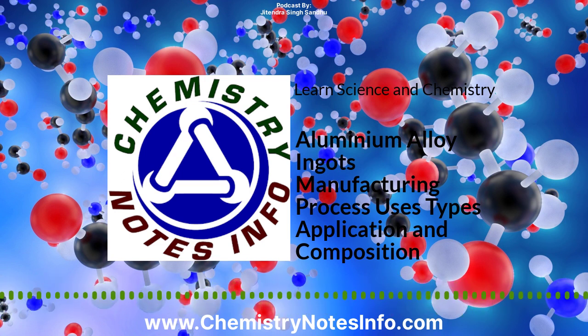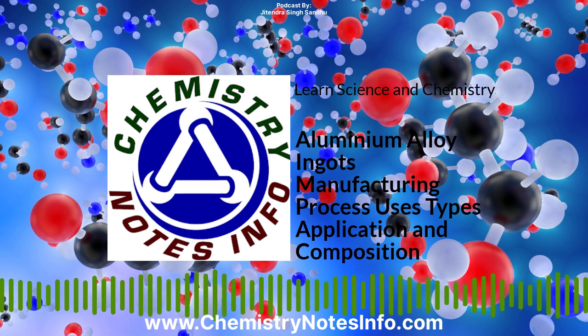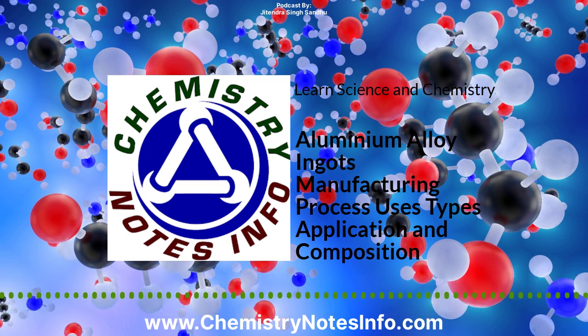And its composition includes silicon about 10.5 to 13%, copper about 0.2 to 1%, magnesium about 0.2 to 0.6%, iron about 0.6%, manganese about 0.5%, nickel about 0.2%, zinc about 0.1%, titanium about 0.2%, other elements as per specific requirement of application or final products about 0.05%, and total of other elements not exceeding more than 0.15%, and the remaining balance is aluminium metal.